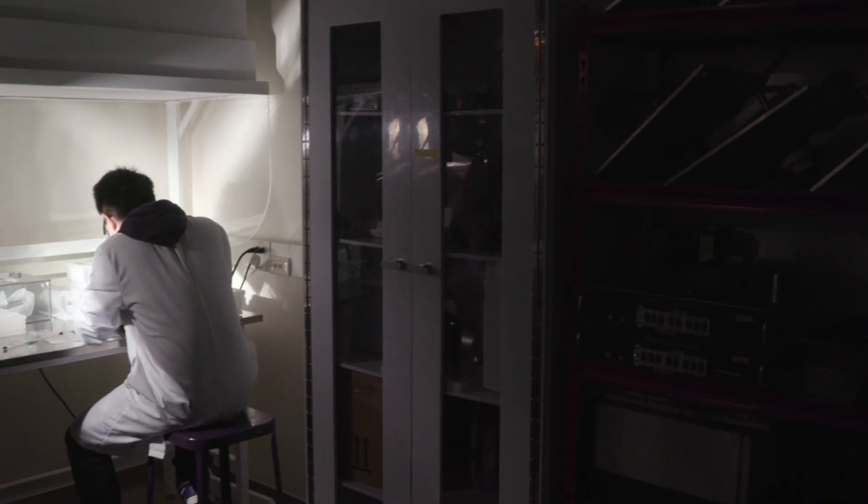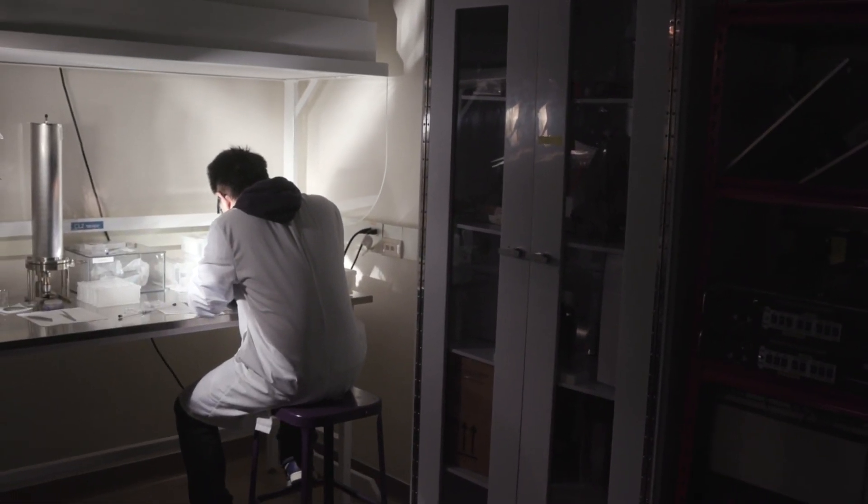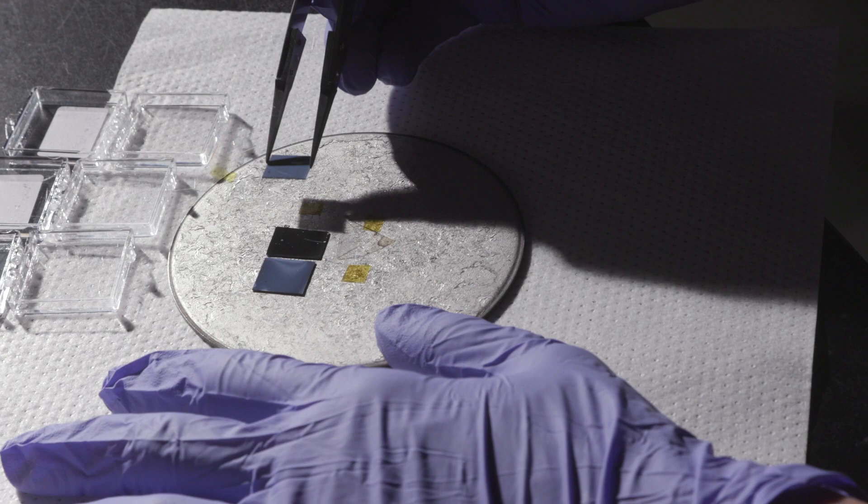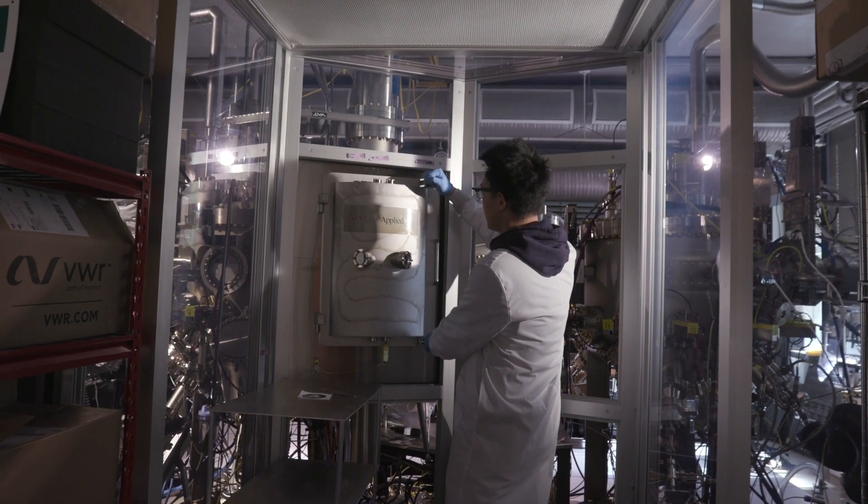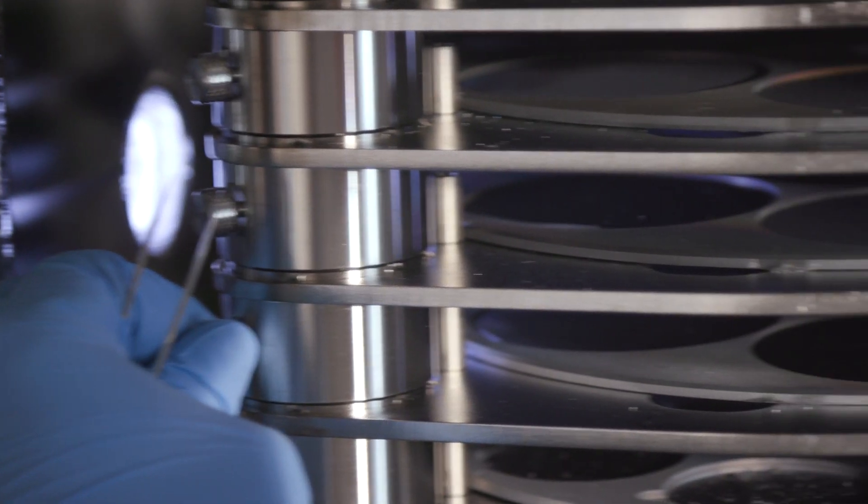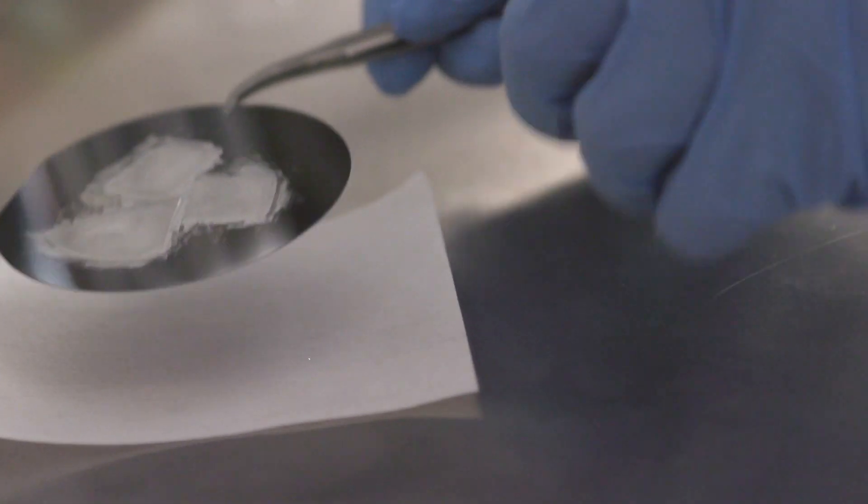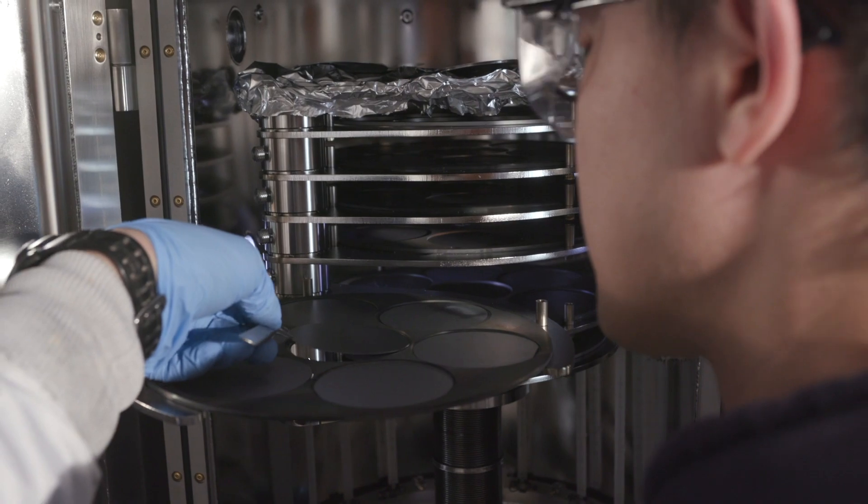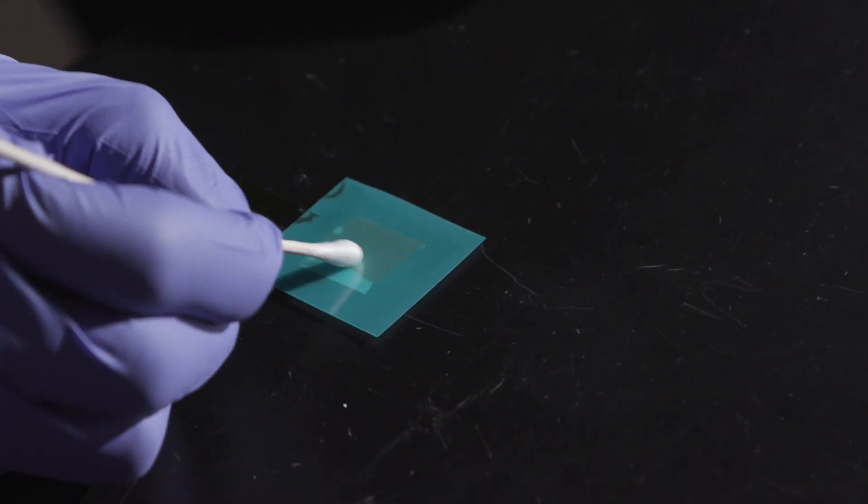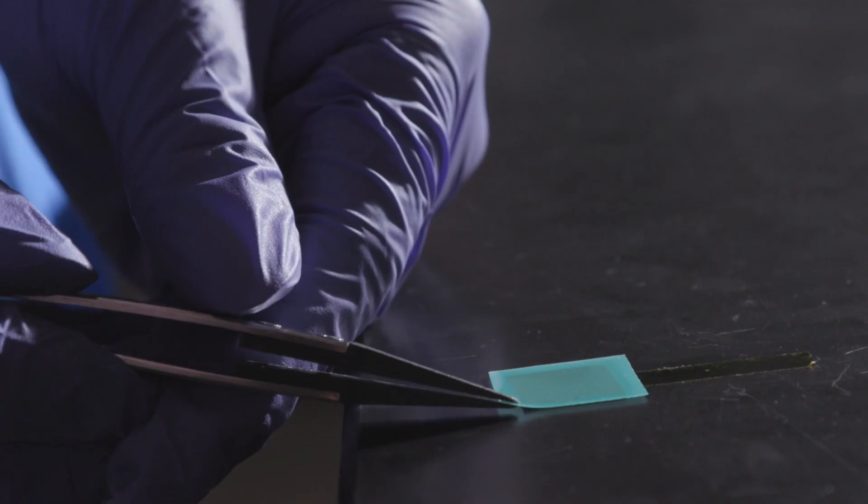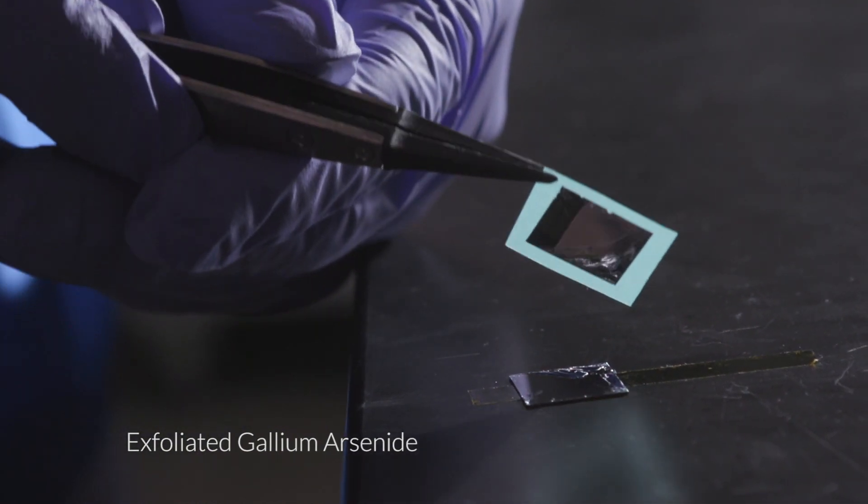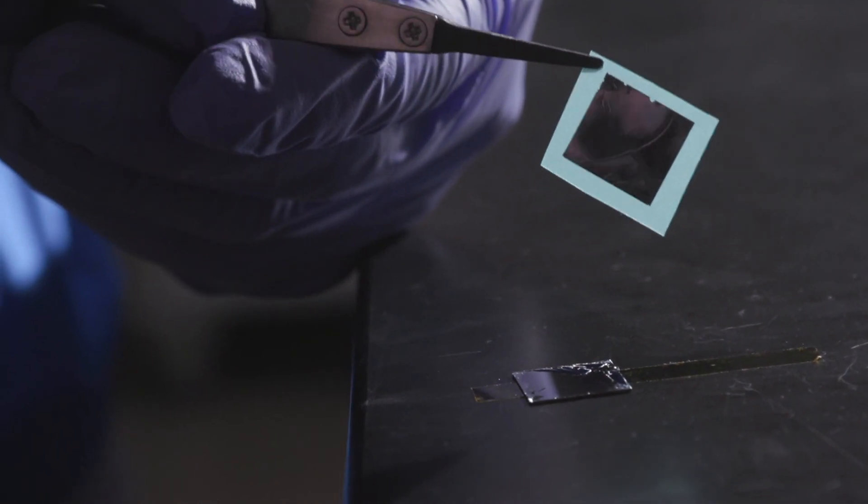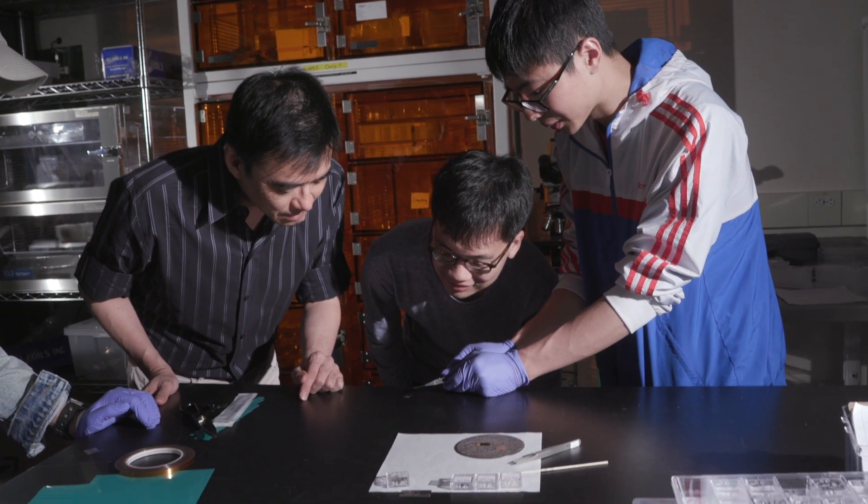Another element of my research is to produce very cheap semiconductor, which used to be very expensive. The first step to make an electronic device is to grow electronic device structure on the wafer. And then we peel off this electronic device out of the wafer repeatedly by reusing one expensive semiconductor wafer.